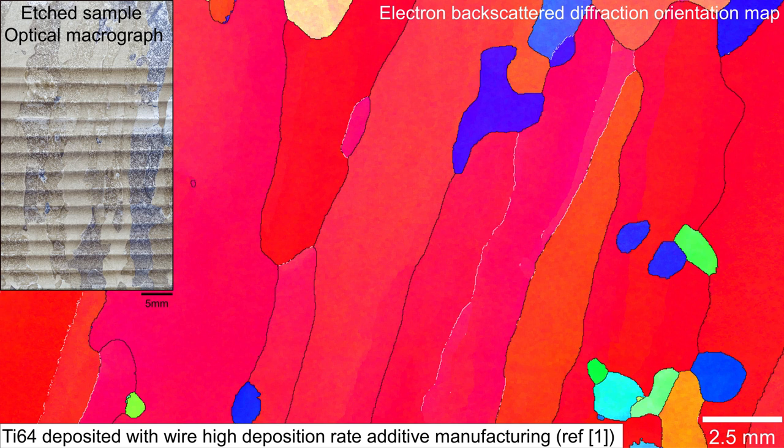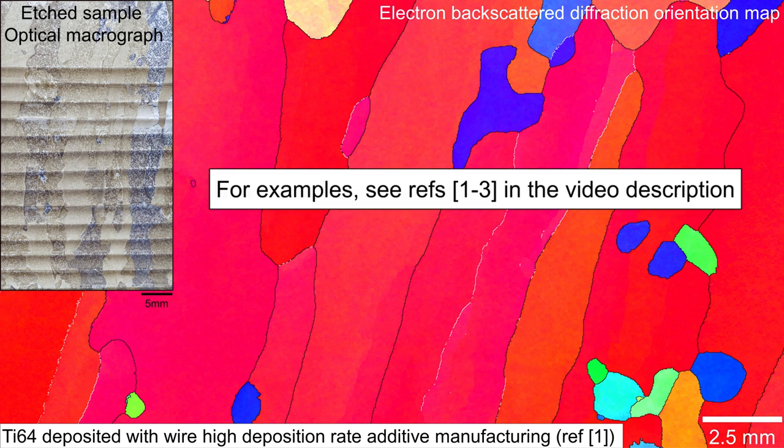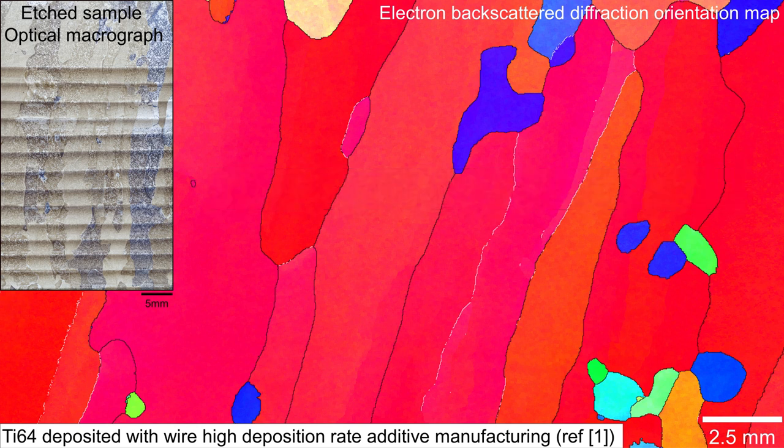A common problem in large-scale 3D printed titanium components is the coarse columnar beta phase grains that form during deposition, which can grow to centimeters in size, producing a heterogeneous microstructure. This leads to mechanical anisotropy and unpredictable damage tolerance. Since the target industry for these materials is aerospace, these detrimental properties are a key issue.